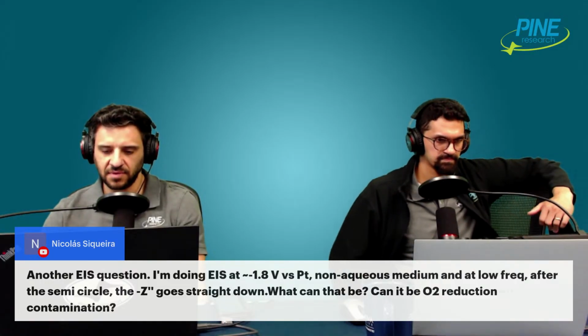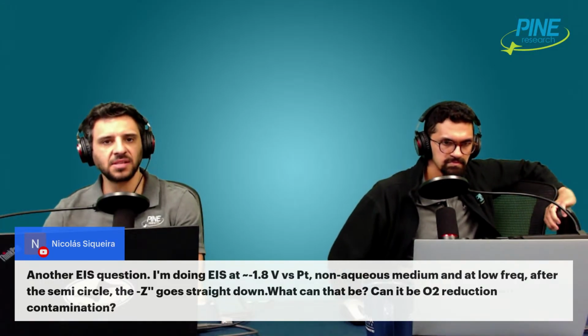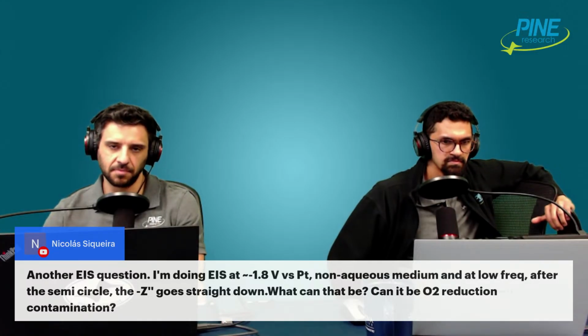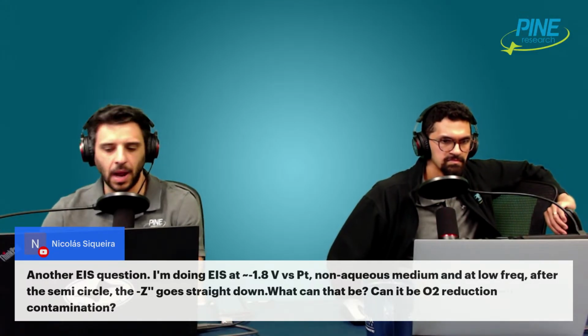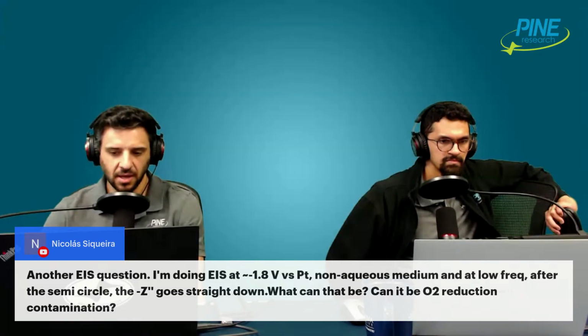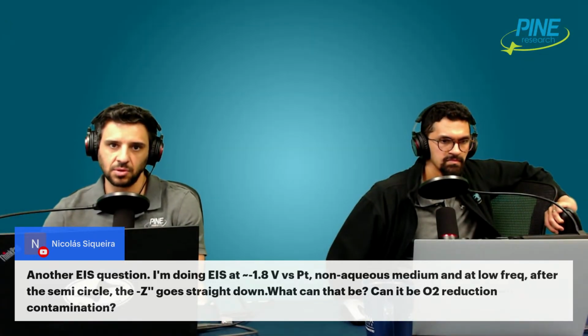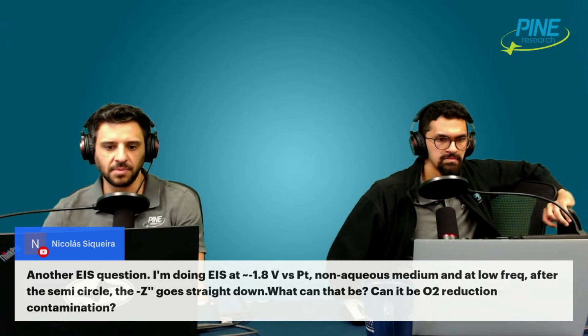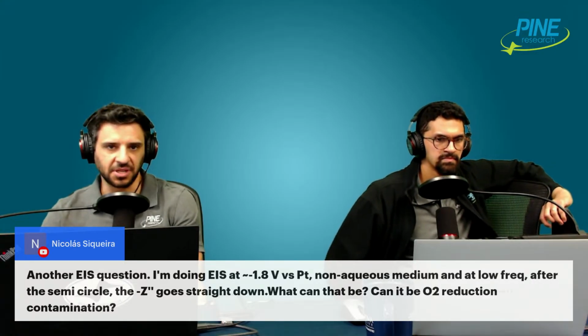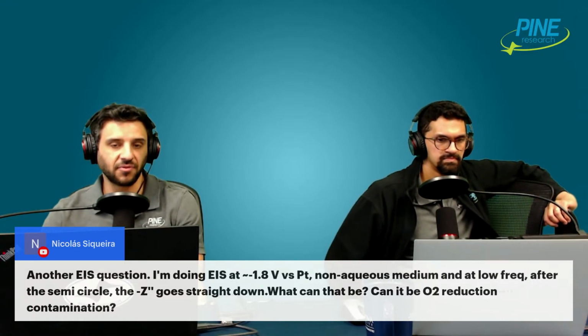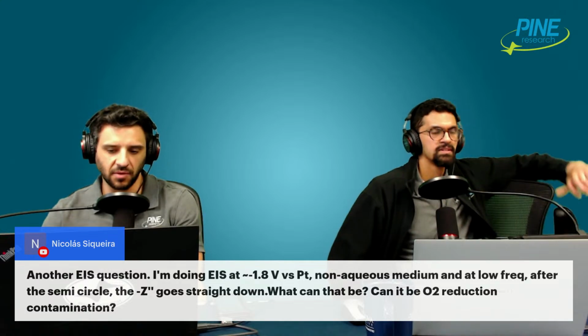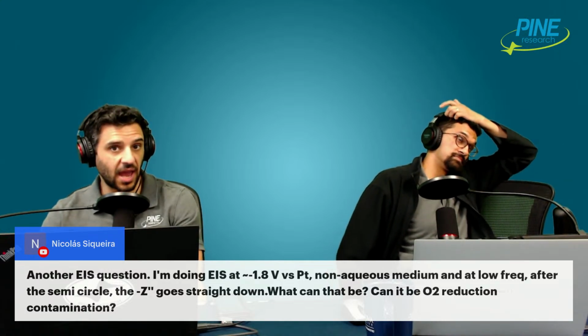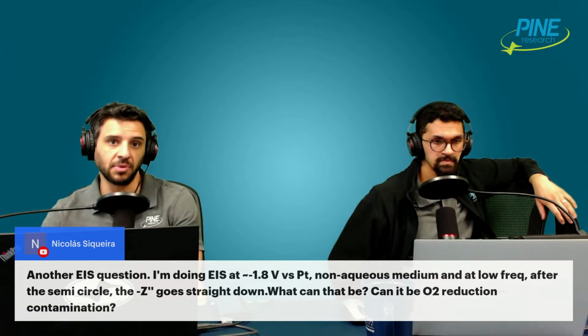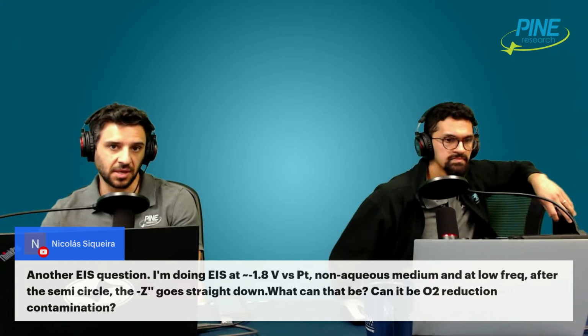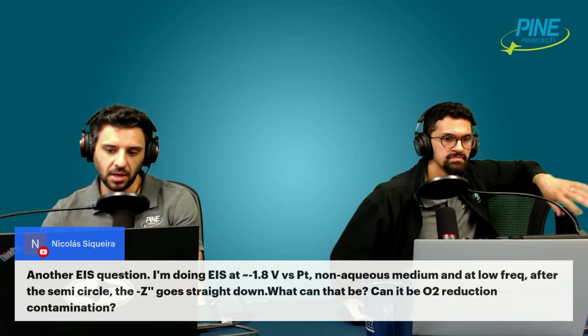First of all, you're at minus 1.8 volts versus platinum. So obviously you have this pseudo reference electrode. Platinum as a pseudo reference electrode is a really, really crappy choice. It's unfortunate. I'm sure there's a good reason why you're using it in non-aqueous. You're sort of stuck with some pseudo reference one way or another. Platinum is a really dicey one to use as a reference. It can kind of swim all over the place. So the first answer is that it might be garbage. It might be absolutely nothing. So run Kramers-Kronig.